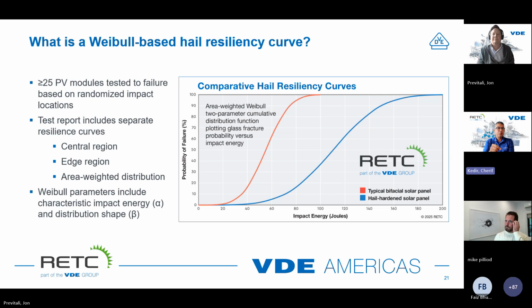Now, one of the things here that's important is the bullets that say that we pick a central region, we impact the central region, the edge, and then do an area weighted distribution, right? So the way to think about it is in a typical hailstorm, if you take a 1 meter squared area or 2 meter squared area, which is typically the size of a module, give or take, if you study a hail storm, you're going to see there's going to be a probability of distribution. There's going to be small hail sizes and large hail sizes, and then those are going to come in various densities. So there are going to be a bunch of them or fewer of them, and they're going to fall in different regions of the module.